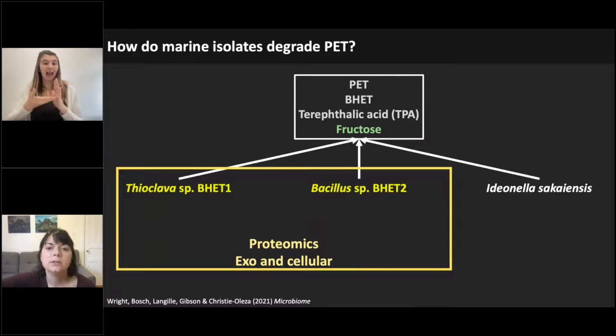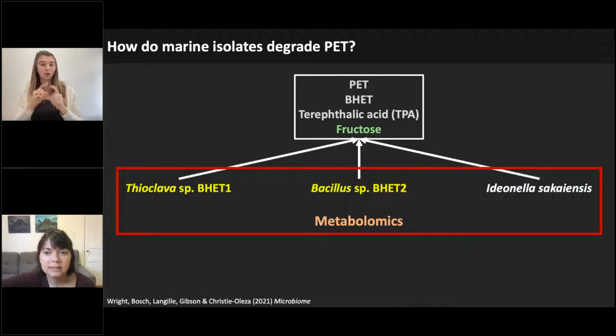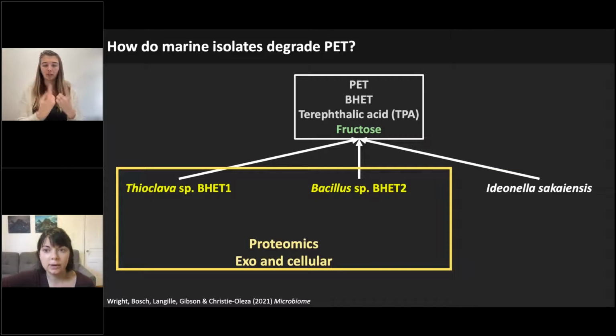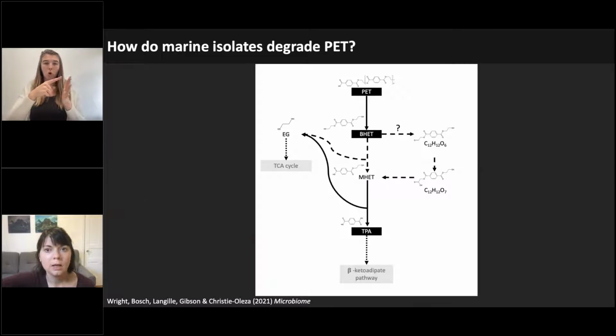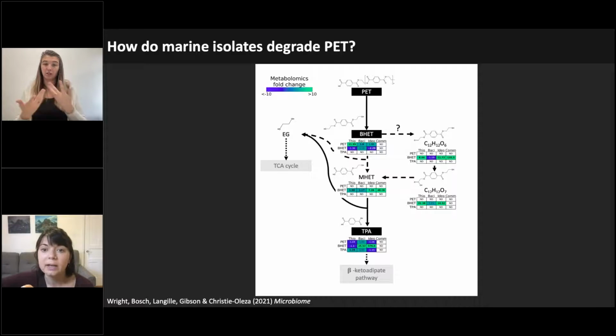So the idea was to detect degradation products and intermediates using metabolomics, and then the proteins or enzymes that each of our 2 isolates was using for degradation using proteomics. So through this combined approach, we were able to get this overall picture of PET degradation. And what we were able to confirm, and what we see here now in green, is that we detect the expected intermediates of PET degradation with each of our bacteria. So Thioclava, Bacillus, Ideonella, and also our community.